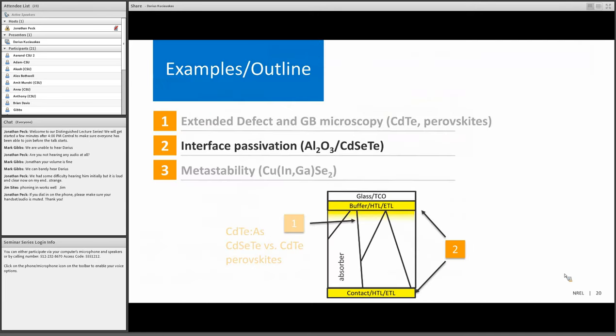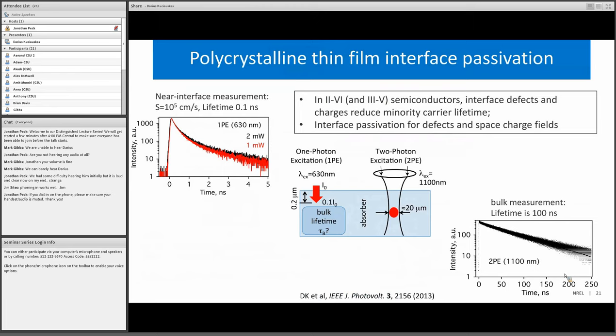Now, passivation. Why is passivation important? As grown, II-VI and III-V semiconductors have high interface defect density and charges. These reduce minority carrier lifetime. In the case of cadmium telluride, whether single crystal, epitaxial, or polycrystalline, it is down to about 100 picoseconds. Very, very short lifetimes, as is shown on the left. When the measurement is taken in the bulk by focusing light in the bulk in the same sample, the lifetimes are 1,000 times higher, 100 nanoseconds. So passivation is needed so that the near-surface electronic properties would be the same as they are in the bulk.